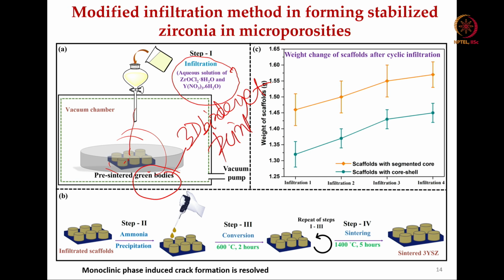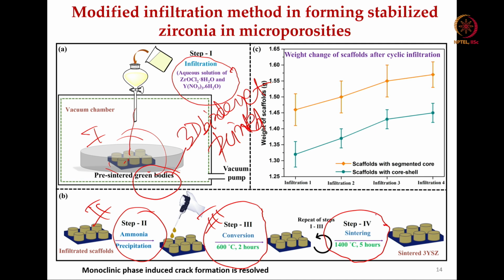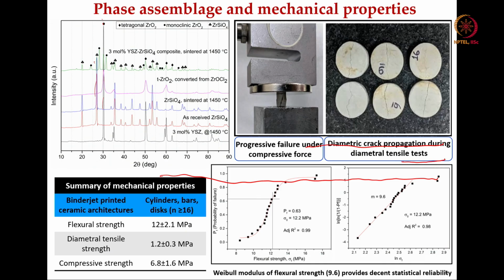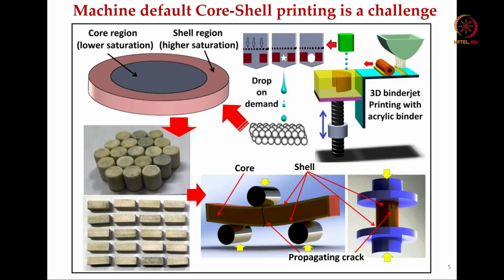So, this is step 1. In step 2, we add ammonia in a drop wise manner. Then step 3, you convert them at 600 degrees Celsius to yttrium stabilized zirconia, so that yttrium is also fused to the zirconium particles. If you repeat step 1, step 2 and step 3 a couple of times, then you stabilize the tetragonal zirconia, or yttrium stabilized zirconia, and then finally you do sintering at 1400 degrees Celsius for 5 hours.